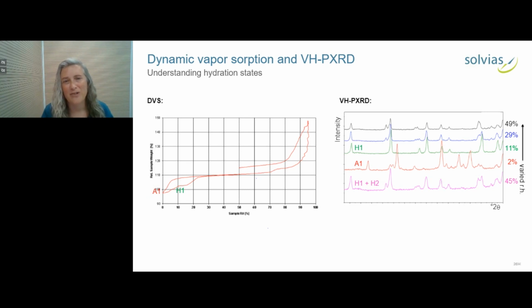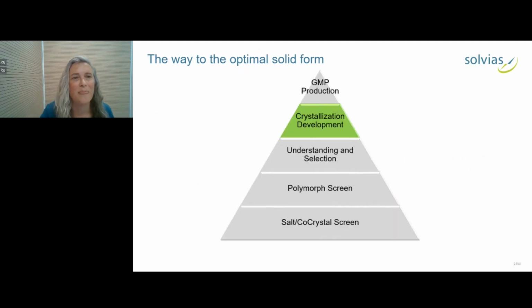And this was very interesting because it led us to realize that our original starting material was actually a mixture of forms. It had hydrate 1 as a component, but was also something else. And then raising the humidity to 29%, you saw the same mixture as initially. And by the time we got up to 49%, you saw pure hydrate 2. So this shows you how you can work together not only to understand hydration states, but sometimes see if you have a pure phase or a mixture.